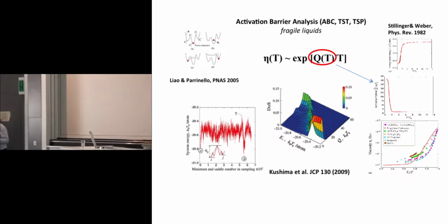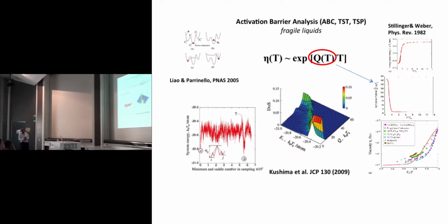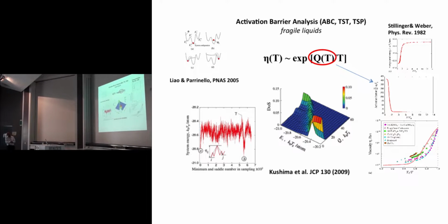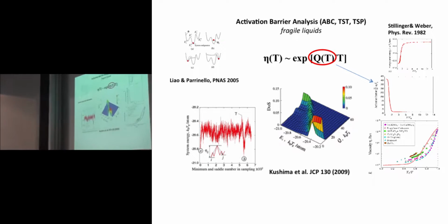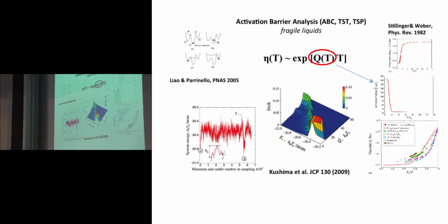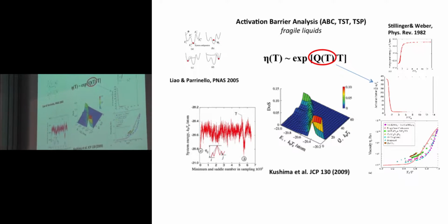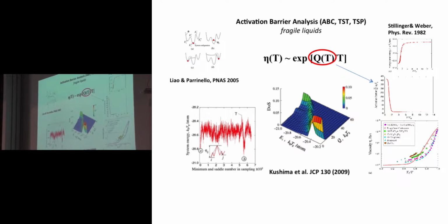It's almost like a two-state system. At high temperature, you have very low activation, and then the activation climbs very steeply up to a high energy level at low temperature. And part of that steepness comes from this inherent structure, which is the one that tells you about the correlation between the temperature of quench versus the energy minimum. That's the inherent structure. So both the activation, which has this kind of behavior, and the thermodynamic contribution play a role in giving rise to this.